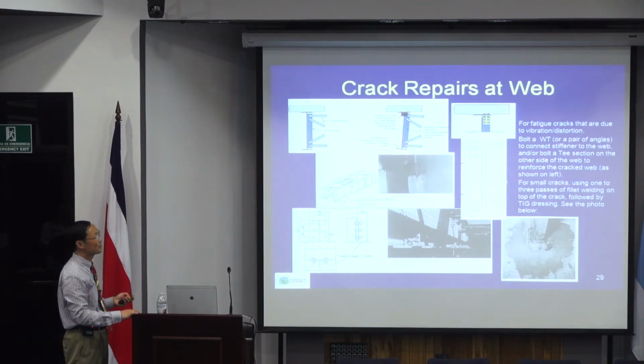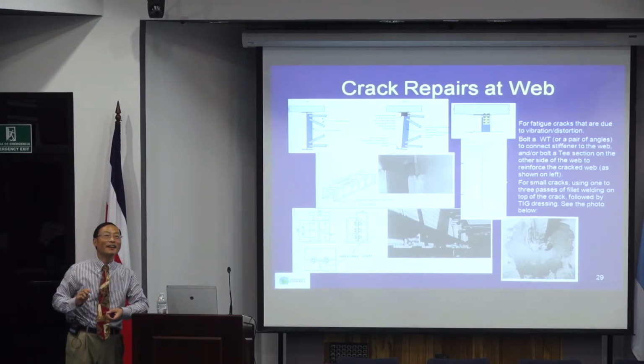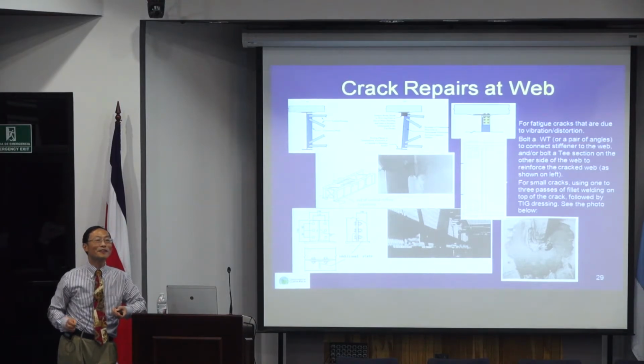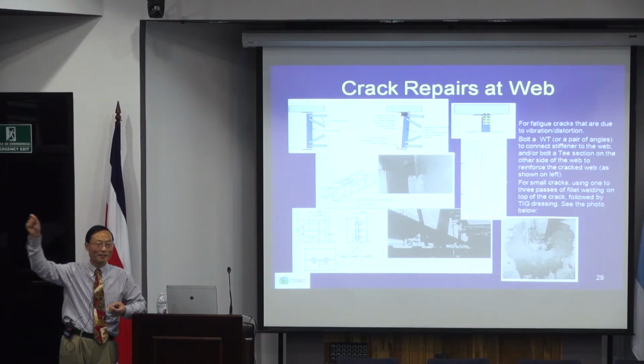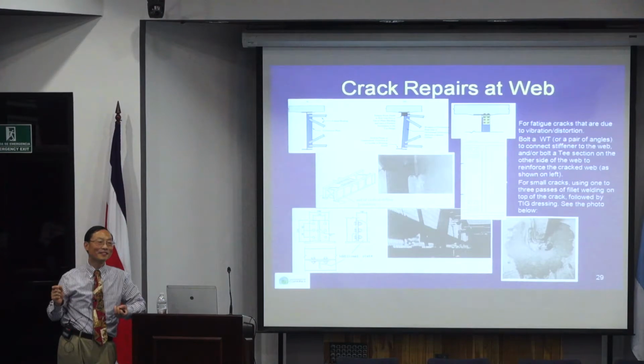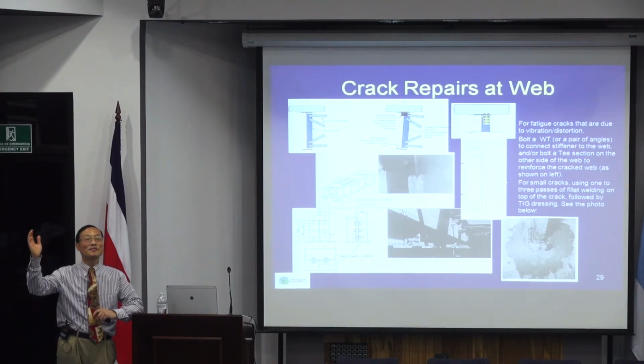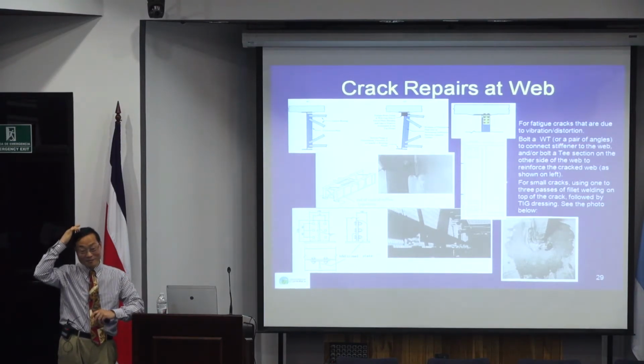Again, these are deformation based. Actually, before, in the 1940s and 50s, people didn't know anything about fatigue. So when they designed stiffeners, transverse stiffeners, they just welded the stiffeners to the web and to the top and bottom flanges. And later people found that welding the transverse stiffeners to the tension flange caused fatigue problems and cracks. So later people said, well, you should not weld stiffeners to flanges. So they just weld to basically just the webs. And that's okay because stiffeners are to stiffen the web. You don't need to connect to the flanges at all.